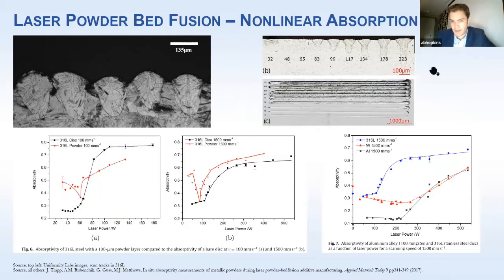Okay, so a little bit more on that. Here are some cross sections at different powers and fixed speed, just melting into a plate. As you can see, you get very different profiles of melt pools. You get this wider profile at the top in 316L, this is. You get this dip, usually wouldn't scan this deeply. So this is when you're moving very slowly or at very high power. And I'll get to some equations later that help define this.